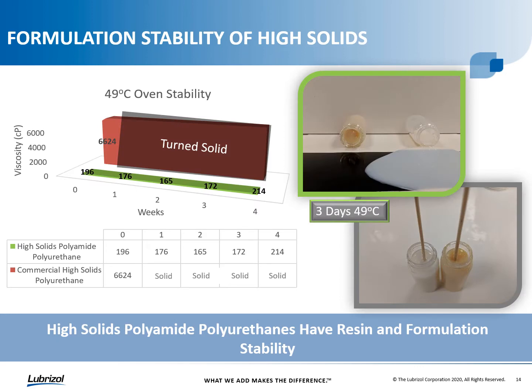In addition to the viscosity challenges, another potential issue with the higher solid systems can just be overall formulation stability. And in this case here, we're looking at accelerated heat age oven stability at 49C or 120F. And here we're comparing the commercial high solids polyurethane benchmark to our formulated high solids polyamide polyurethane coating. In the picture on the right, you can see after just 3 days at 49C, the commercial high solids material has pretty much solidified, whereas the high solids polyamide polyurethane remains completely fluid and pourable.